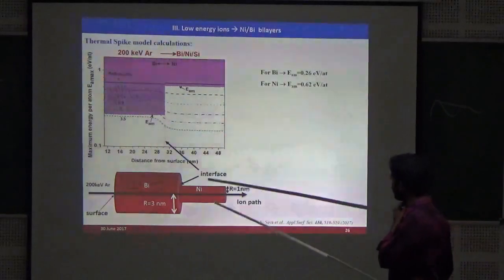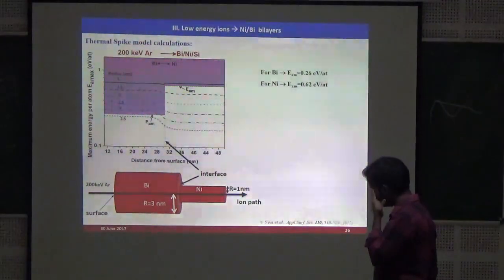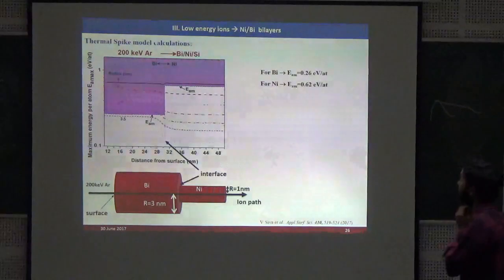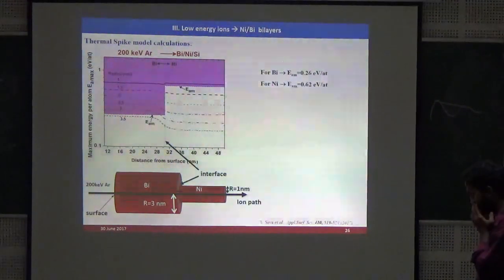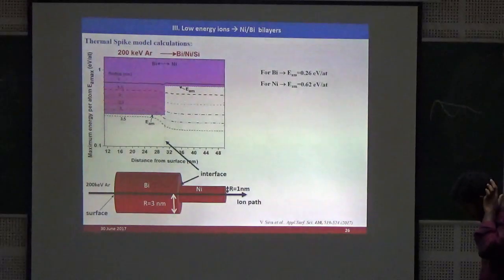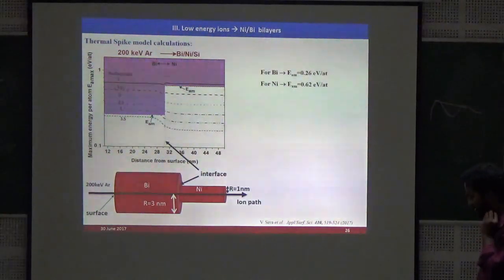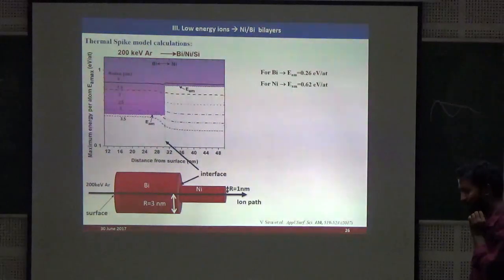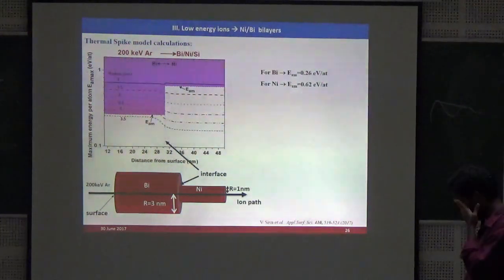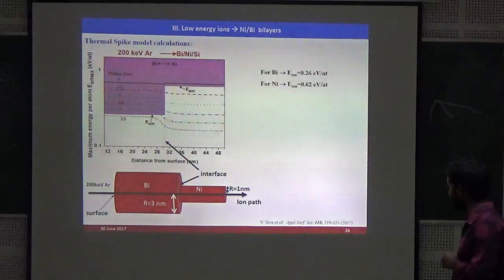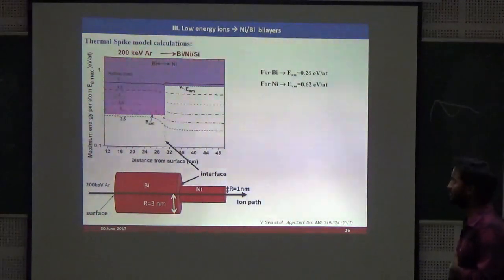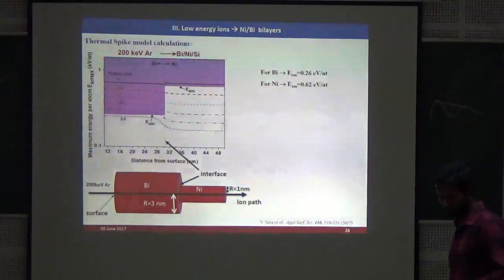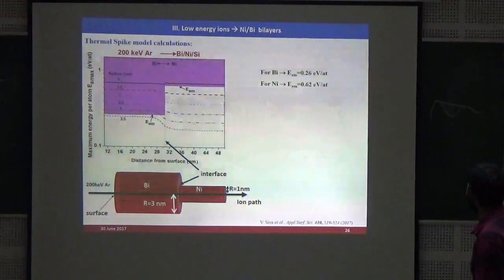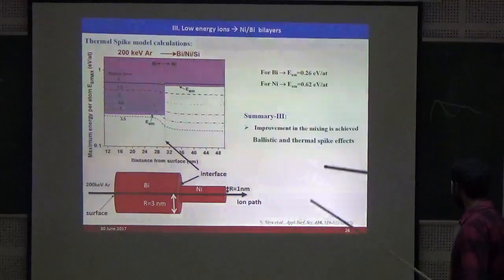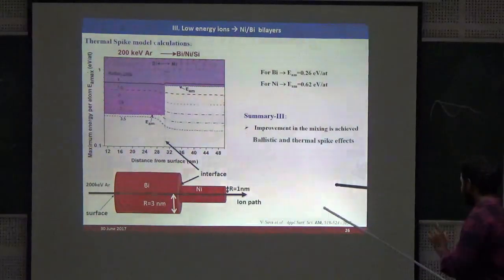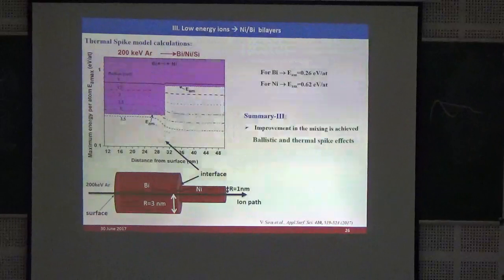Okay, so we have given the amount of energy per atom here. In case of nickel, it reaches 1750 Kelvin, which is a little higher than the melting point of nickel. In case of bismuth, it reaches around 700 degrees. So in this case, the enhancement in the mixing is due to a combination of both ballistic effects and thermal spike effects.